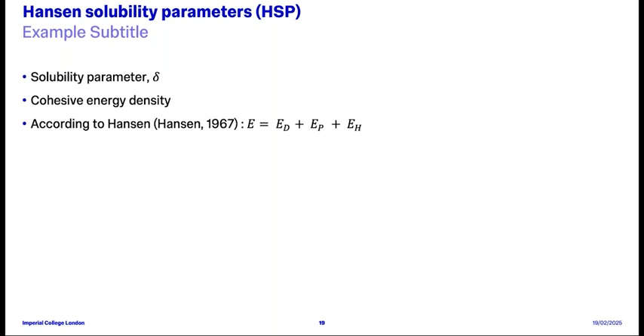Solubility parameters are related to the cohesive energy density, and according to Hansen, they can be divided into three different components. The first is the dispersive component, which represents the contribution of van der Waals forces. Next, the polar component, which describes the electrostatic interaction between dipoles and is based on the overall dipole moment of the molecules. And finally, the hydrogen bonding component, which describes the specific interaction involving a directional bond between an H donor and an acceptor. As a rule of thumb, the more similar the Hansen solubility parameters between two components are, the more compatible they will be.